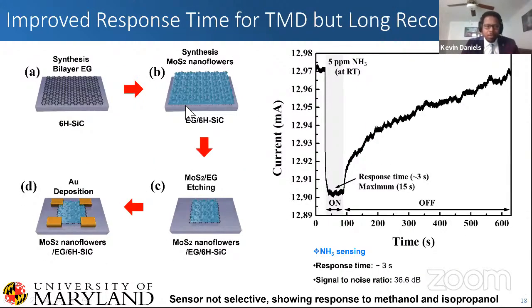And as you can see here, this is sort of the process. We have the synthesis of epitaxial graphene. We synthesize these nanoflowers, and we make this four-contact gas sensing device. And what we saw is in the presence of ammonia, just 5 parts per million, we have a very, very quick response in 3 seconds, which is really unprecedented for most sensors, especially for a transition metal dichalcogenide sample. And with it being on graphene, we saw that it has really good signal to noise ratio.